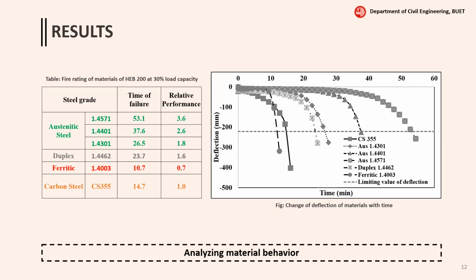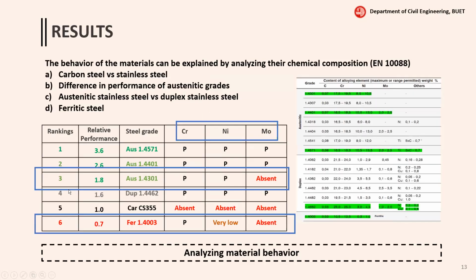Moving on to the results. Let us first analyze the behavior of the materials for fixed loading in a fixed section. It is clear that except ferritic, all the other 4 grades of stainless steel outperformed carbon steel. There is a difference in performance between the austenitic steels, where one is almost 4 times that of carbon steel and the least one performed twice that of carbon steel. The performance of duplex was in between austenitic and carbon steel. This behavior of the materials can be explained from their chemical composition.